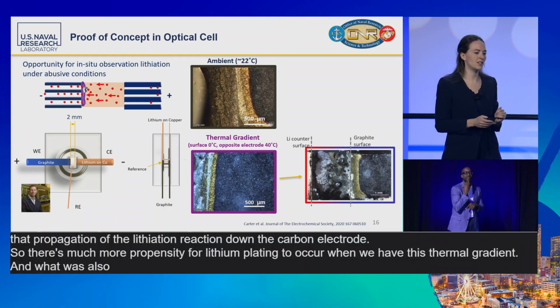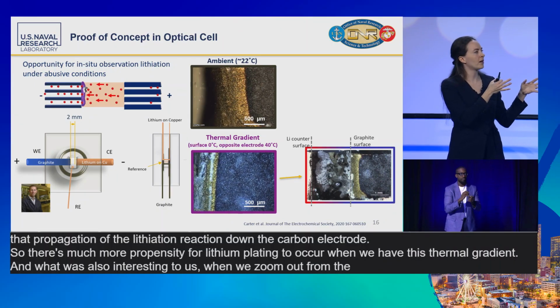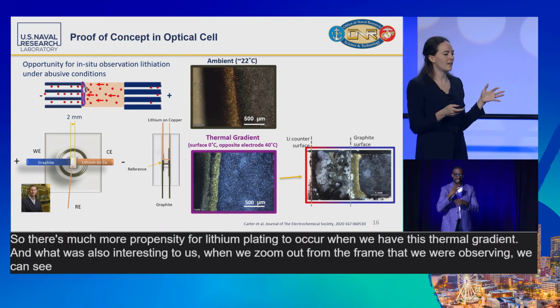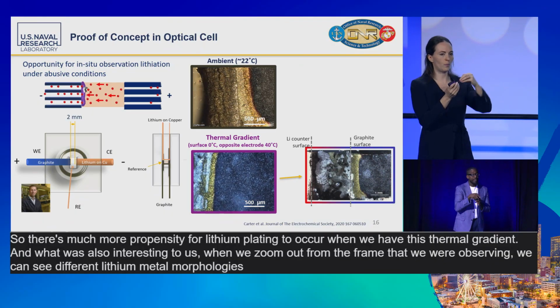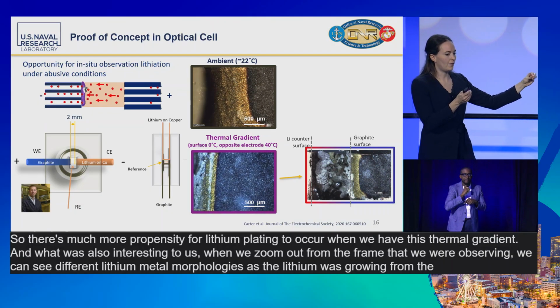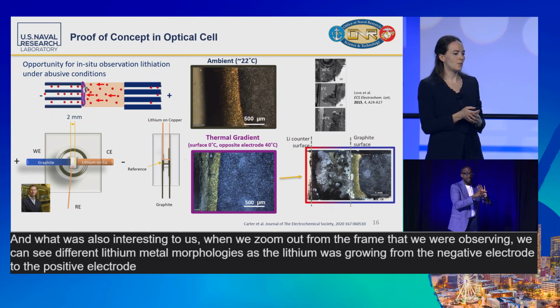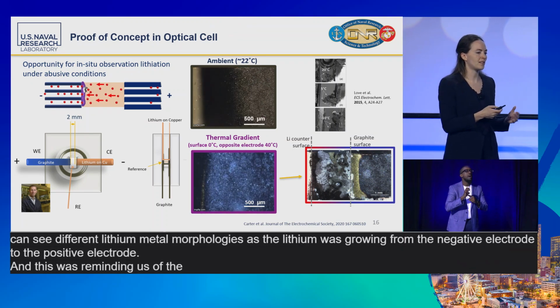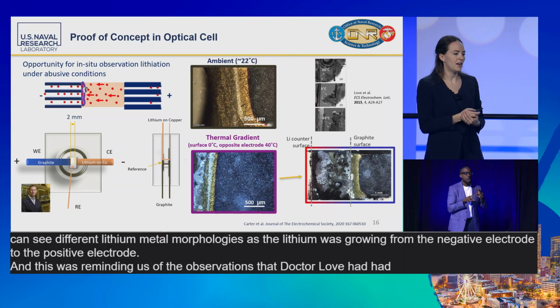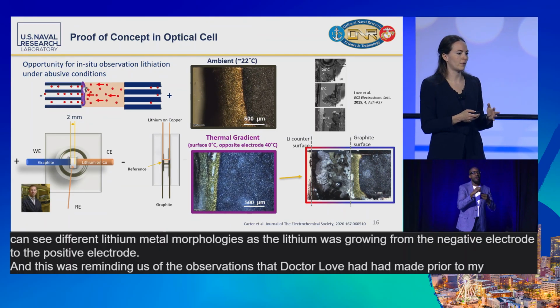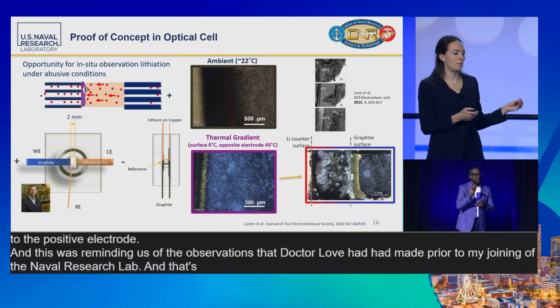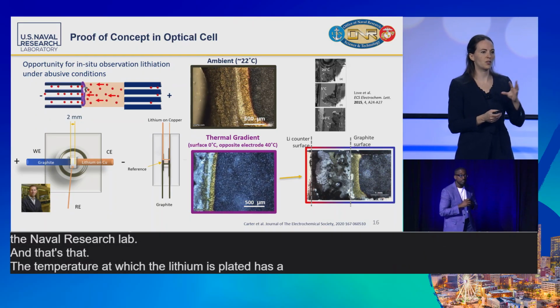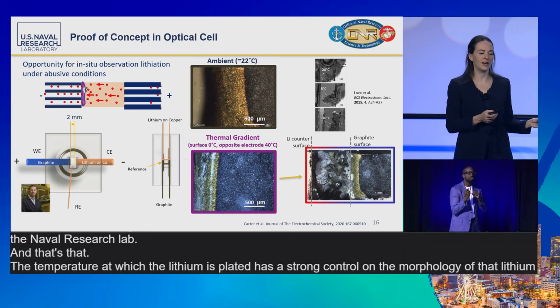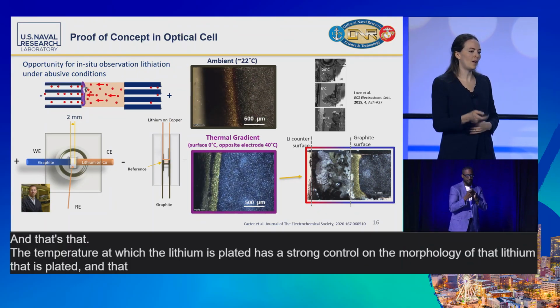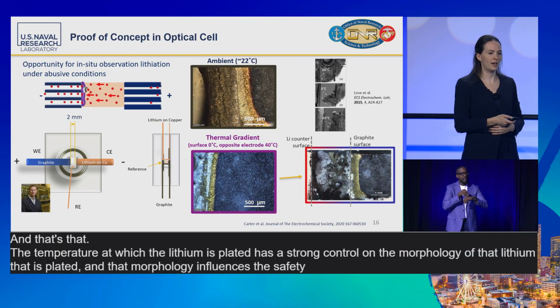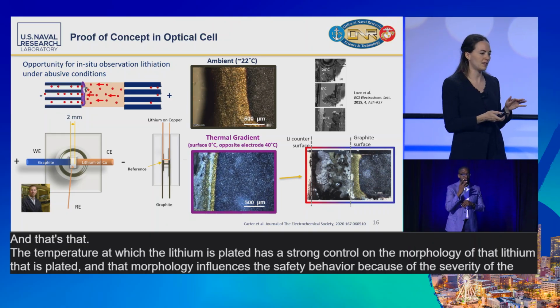And what was also interesting to us when we zoom out from the frame that we were observing, we can see different lithium metal morphologies as the lithium was growing from the negative electrode to the positive electrode. And this was reminding us of the observations that Dr. Love had made prior to my joining of the Naval Research Lab. And that's that the temperature at which the lithium is plated has a strong control on the morphology of that lithium that is plated. And that morphology influences the safety behavior because of the severity of the shorting event.